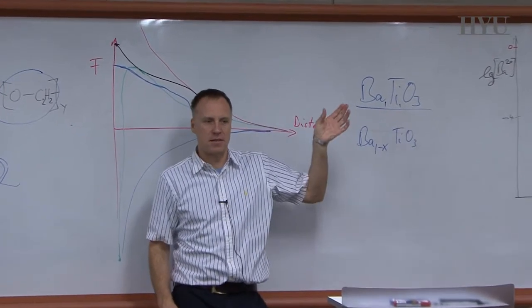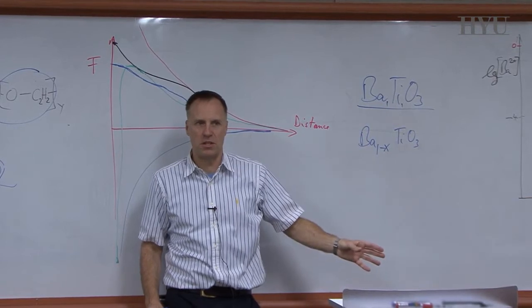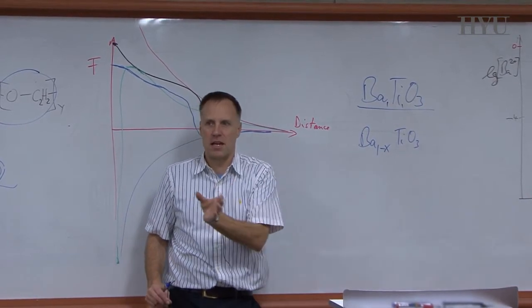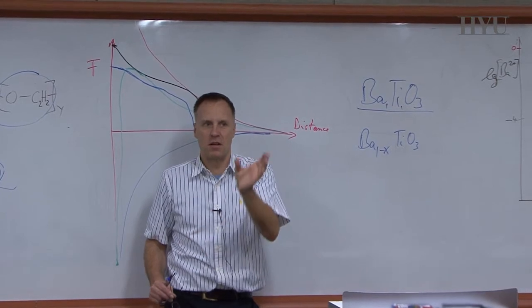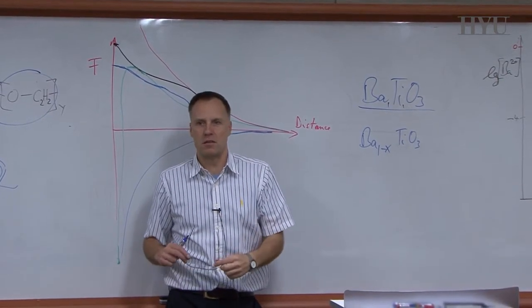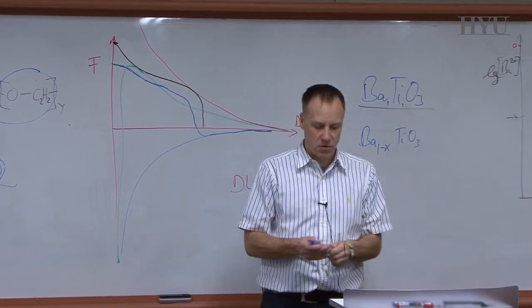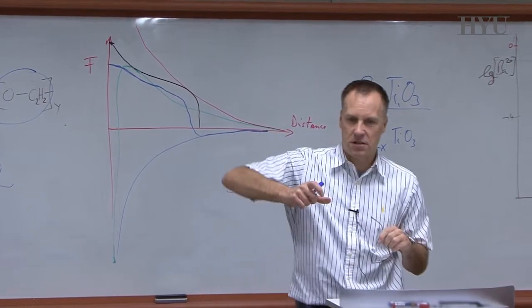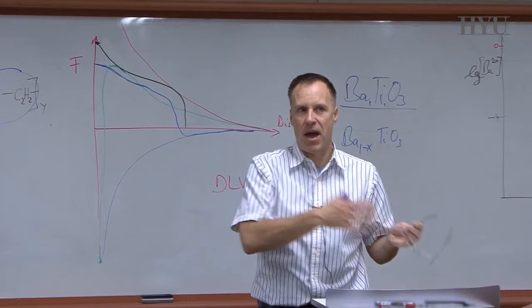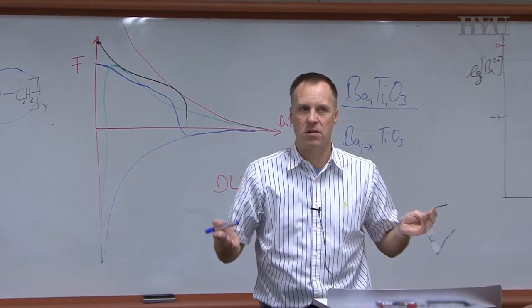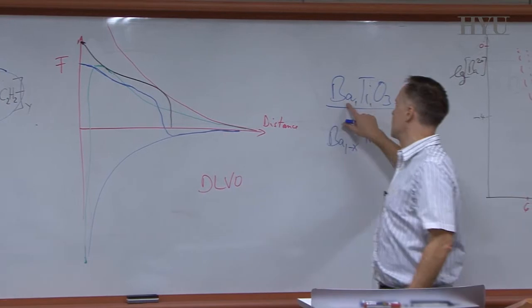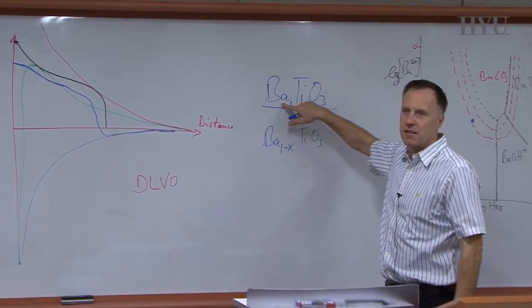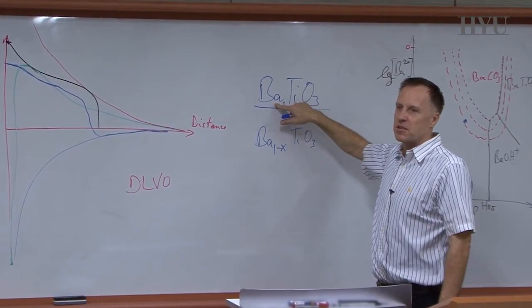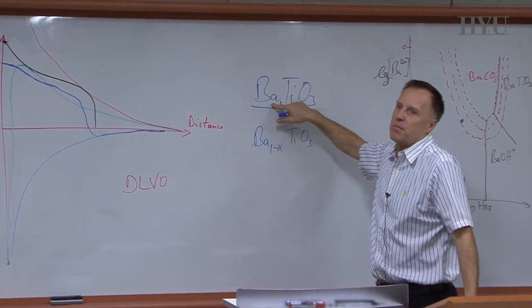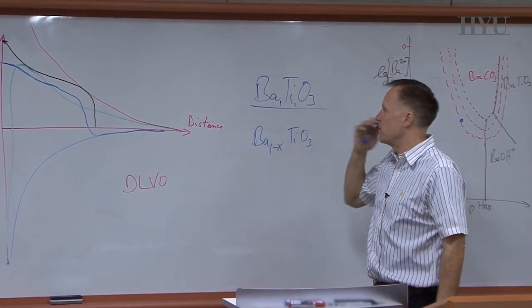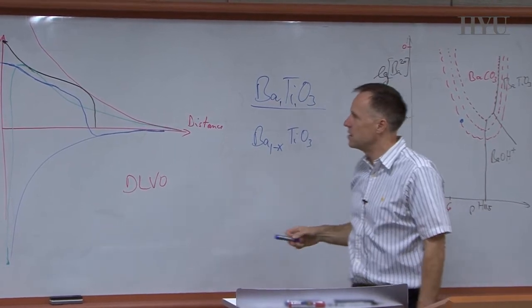And this means it starts from the beginning when you weigh in your material, and through the entire process, whatever you do, you have to watch out that you don't lose the barium. And so this one process that we talked about earlier, where you just wash it and decant the barium ions, might be bad. You might lose too much barium. Of course, you can compensate by starting with something that is barium rich, and then 2% loss of barium ions wouldn't matter if you started 2% rich in barium ions. So you can adjust for these things, but you have to watch out for a lot of little details.